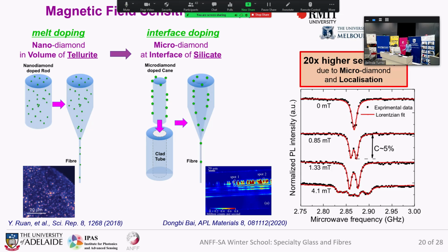We were very happy to have a more robust doping technique, but it also led to a 20 times higher sensitivity, because we used micro diamond particles which create a higher localization and concentration of NV centers in one spot. Also, because we localize the diamond particles only at the interface between an inner and outer region, we have less scattering of the fluorescence as it travels along the fiber.